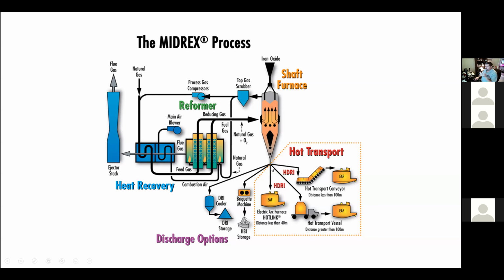In some cases, the direct reduction plant is right beside the steel plant. And so they feed the material while it's still hot, up to 600 degrees, directly into the electric furnace. Some people also use pneumatic transport, refractory lined containers to transport it, or hot transport conveyors. So there are a lot of different ways, if the direct reduction plant is located adjacent to the steel shop.